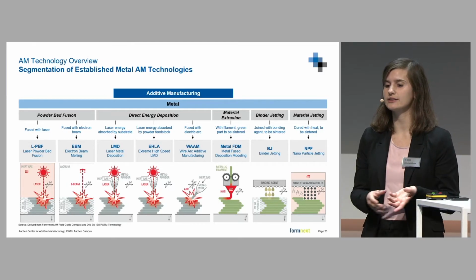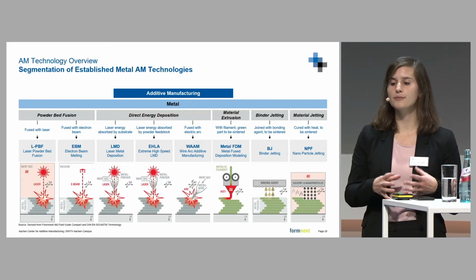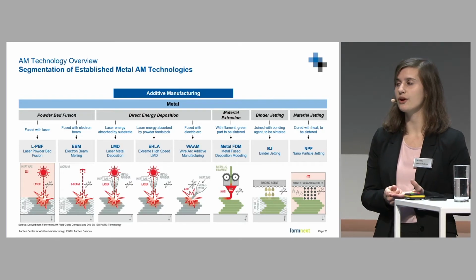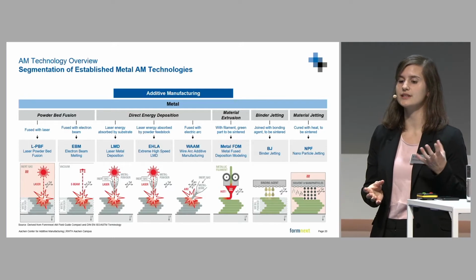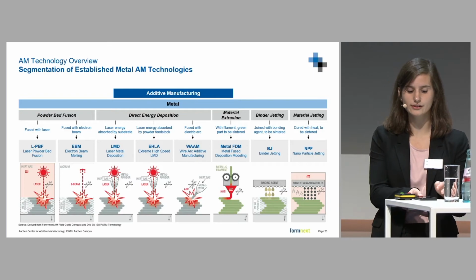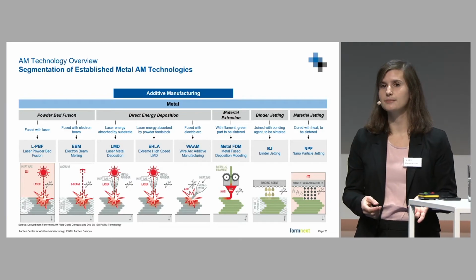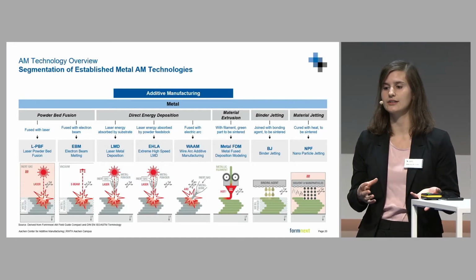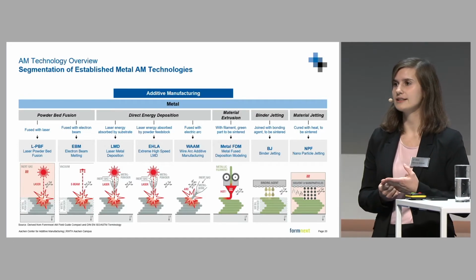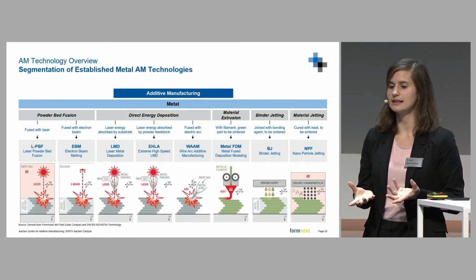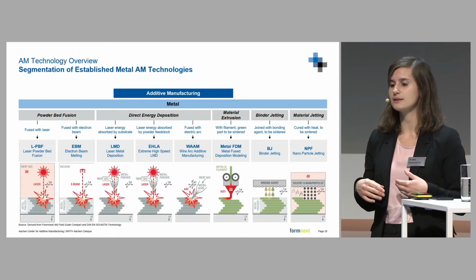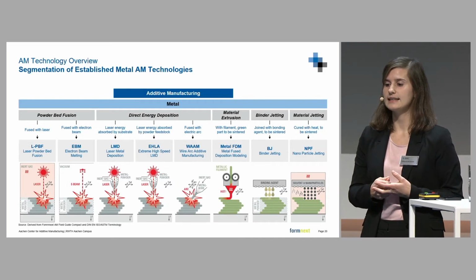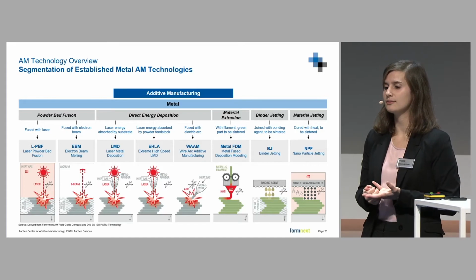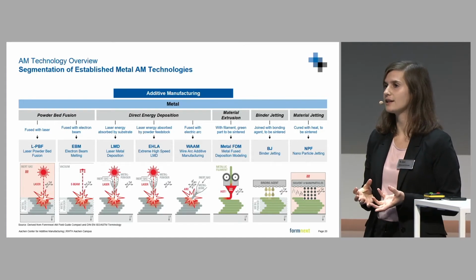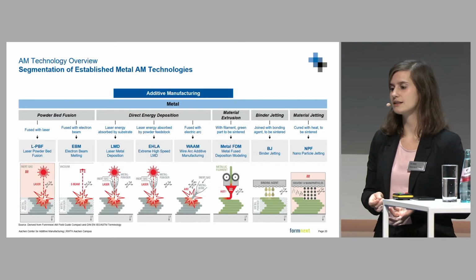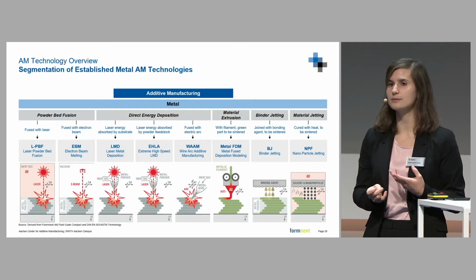So how do those different categories differ? On the left-hand side, we have a powder stock where energy is inserted in order to fuse powder to a component. So we have laser powder bed fusion, where you use a laser as an energy source, and we also have electron beam melting, where an electron beam is used as your energy source. And then in the middle block, we have direct energy deposition, where we don't have a powder stock, but the material is deposited together with the energy source. Then we have material extrusion, where a filament is being deposited. We have binder jetting, where powder is bonded with a binding agent. And we have material jetting, where the material is cured with heat.